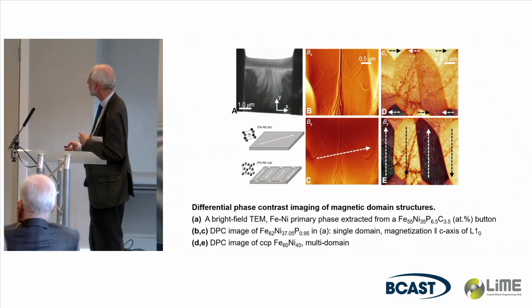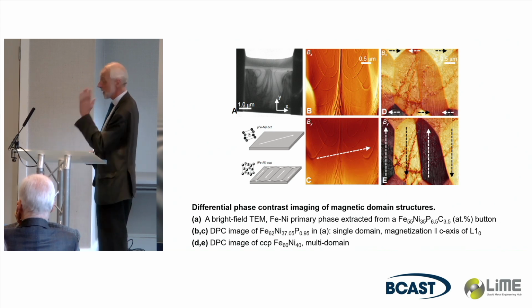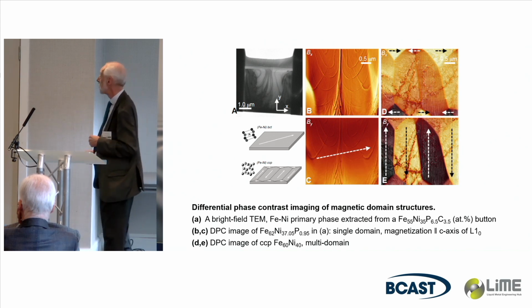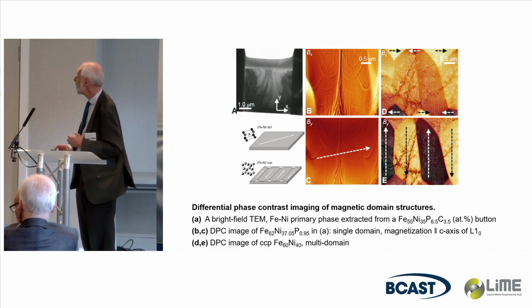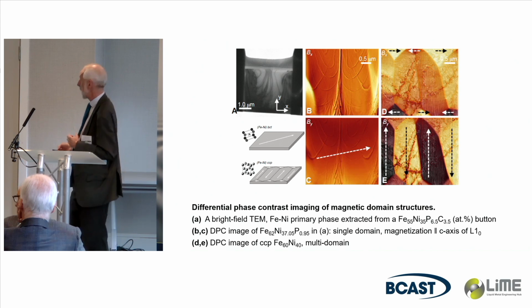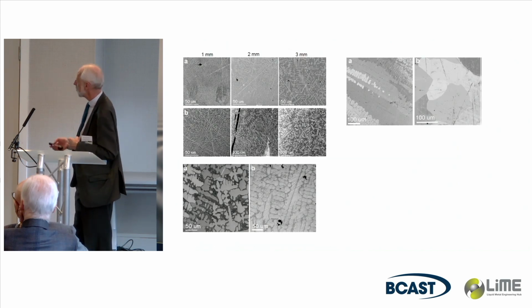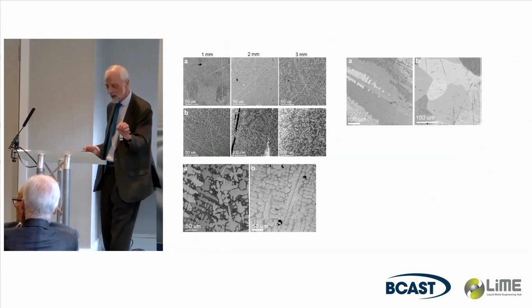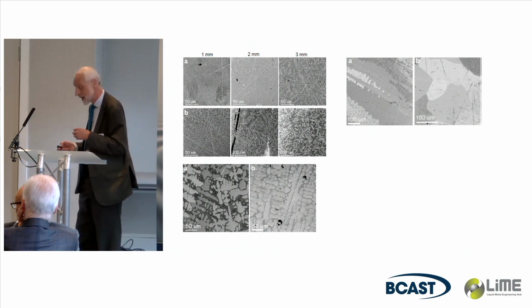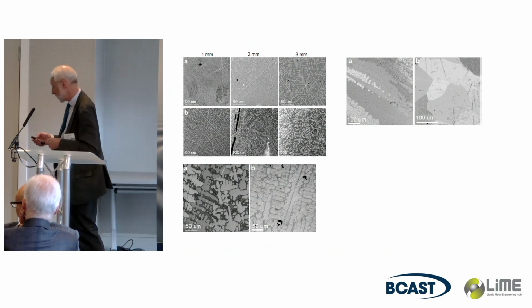So this is quite substantial and quite different from the up and down domains balancing out in just a simple face-centered cubic soft magnet. And from that initial sample with very fine dendrites, we could adapt the composition and get a larger volume fraction of the dendritic phase.